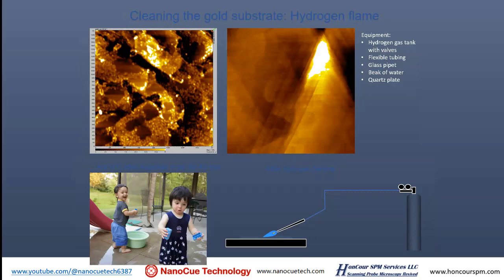Since we mentioned something about flame, fire is a very good way to clean anything. It's a good way to clean glass, and it's a very good way to clean gold substrate. The one on the left upper corner, I collected that image when I was doing a demonstration at University of Illinois, Urbana-Champaign. I opened up a piece of gold, and it was clean. And after 45 minutes, this is what it looked like. Those little grapes, they are not gold. They're contaminations from the air. I just watched them grow on the surface.